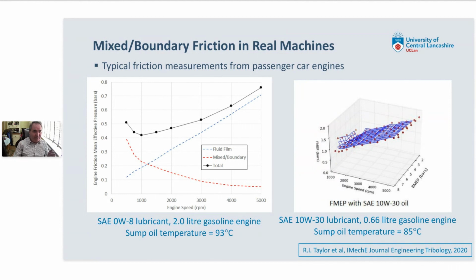And this is an example where you've got mixed and boundary friction. In fact, in the reference quoted here, the friction of this engine was split between fluid film components and the mixed and boundary components. We can see that mixed and boundary friction actually becomes greater than fluid film friction for speeds less than about 1200 RPM. That was with a fairly old 1990s 2-litre gasoline engine, and it was a fully warmed up engine. The sump temperature was about 93 degrees centigrade. So we can see a considerable amount of mixed and boundary friction at low speed in this engine.